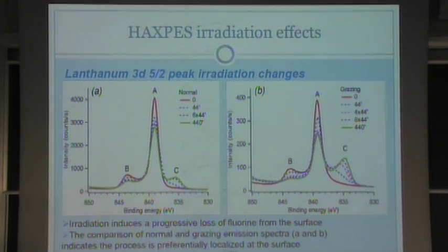So we've made irradiation experiments. And here, as you can see, with time a new feature appears on the right side of the spectra. This feature is actually related to free lanthanum bonds, so fluorine vacancies. There were 2 experiments done, normal and grazing, and the experiment at grazing incidence is more surface sensitive, and you can see that the peak is higher, which means these changes are on the surface and not in the bulk. So it's like light-induced changes.